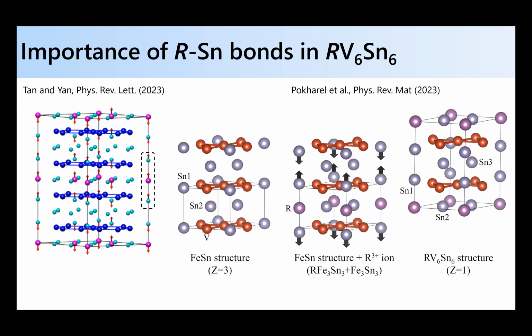And so if you look at what's actually going on in the charge order phase, the atoms that are moving are not really the vanadium atoms. They move a little bit, but the main actors are these tin and scandium ions, okay? And they're moving along the c-axis, okay?